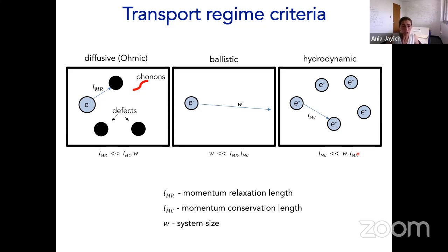So the way to get to this regime is to investigate samples with long momentum relaxing lengths, so very clean samples, where you can tune the temperature to take you from, say, diffusive at high temperature through hydrodynamic. Once you get to very low temperature, this momentum conserving length is typically going to be longer than the length of the device as well. So at low temperatures, you'll be in the ballistic regime. But if you have a clean enough device, as you go from high temperature to low temperature, it's possible to enter this hydrodynamic regime.